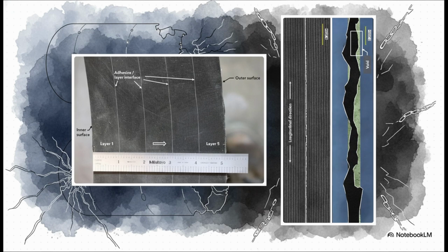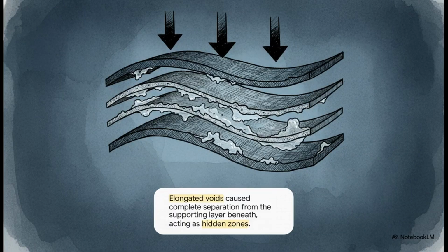See those dark, jagged patches? Those are entire areas where the glue completely failed to bond the carbon fiber together. To put it as plainly as possible, these elongated voids created discrete, completely hidden zones inside the hull where the heavy, 1-inch thick layers of carbon fiber were effectively unattached to each other. Under normal circumstances, that adhesive is supposed to seamlessly transfer the massive compressive loads right through the 5-inch wall. But with these huge voids present, the layers were essentially acting independently, which vastly reduced the hull's overall structural integrity.